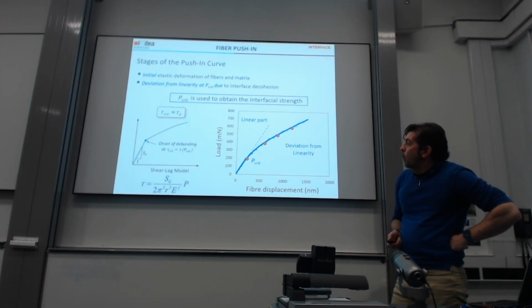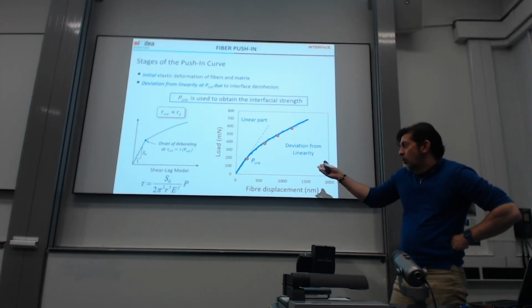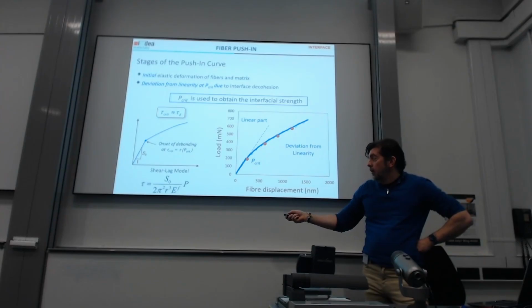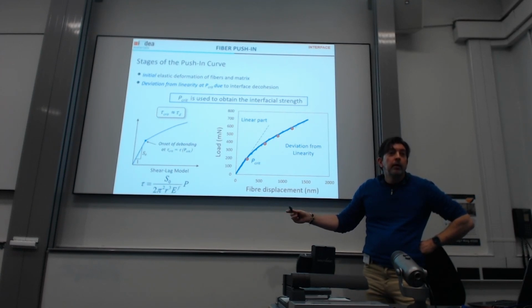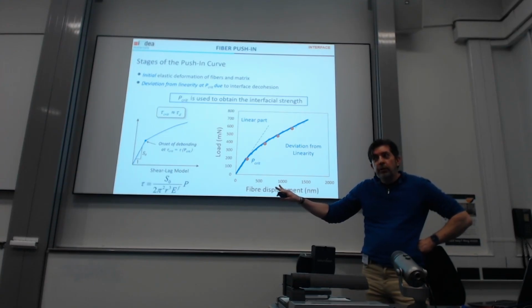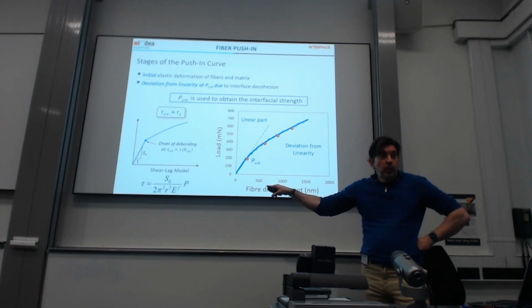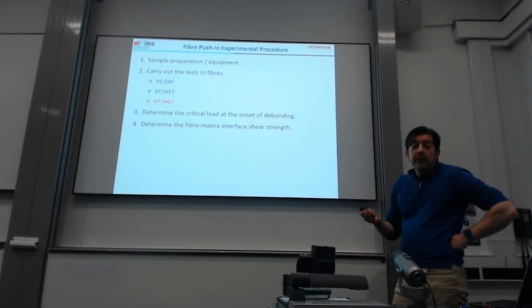And this can be analyzed with what is called the shear lag model, to calculate the interface shear strength. I will tell you a bit, because this depends on the stiffness, critical load, radius of the fiber, and elastic modulus of the fiber. It's a simple approximation, and I will tell you a little bit about the problems of using this model. So we move to the experimental procedure.